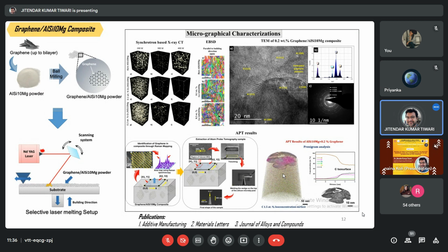Okay, so if you talk about TEM, transmission electron microscopy, in transmission electron microscopy you see around a 50 nanometer thick layer, because that particular thickness is electron transparent, and you are seeing the 3D information in 2D. So that is the idea of transmission electron microscopy. But if you want to see any information as it is, like it is in 3D, then we want to see at nanoscale in 3 dimensions. So for that purpose, we can use the atom probe tomography technique.